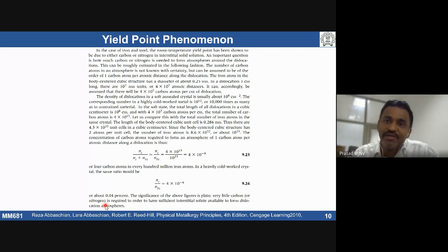Because that strain depends on how much carbon you're talking about, how much dislocation density is there. Accordingly, one has to decide how much strain is required for the skin pass. Typically for low carbon steels, it lies anywhere between 1 to 2%. That's one of the solutions to control or minimize the stretch strain bands.